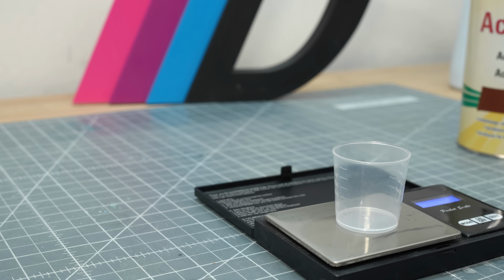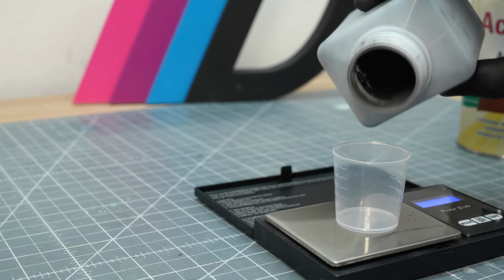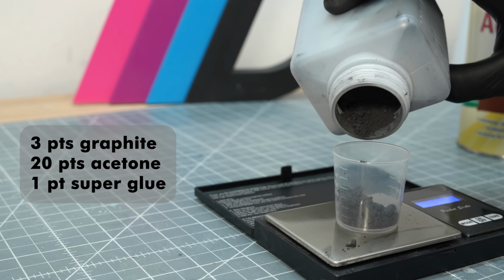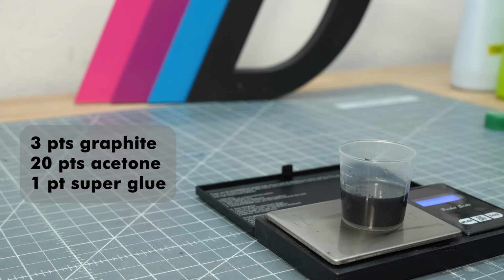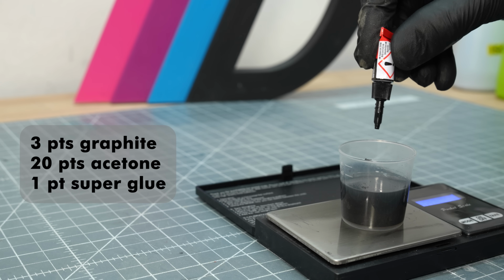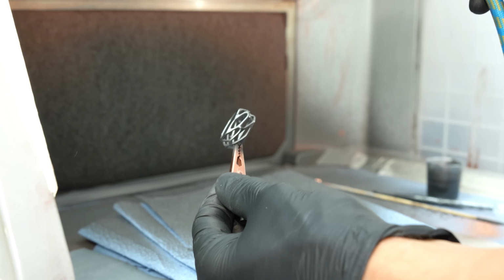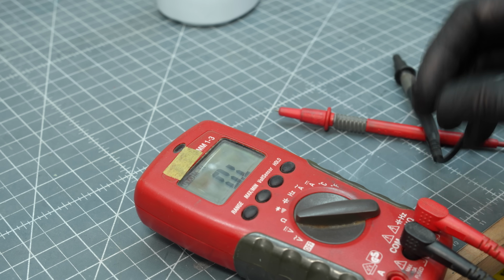Okay, my recipe for DIY graphite paint is as follows. Take 3 parts graphite powder, 20 parts acetone and 1 part superglue. Mix, airbrush, polish, measure, 600 ohms. Yay!